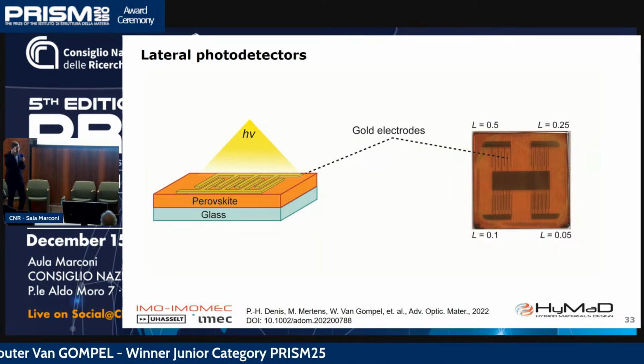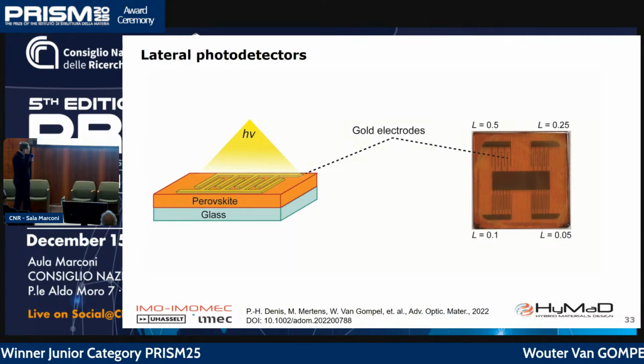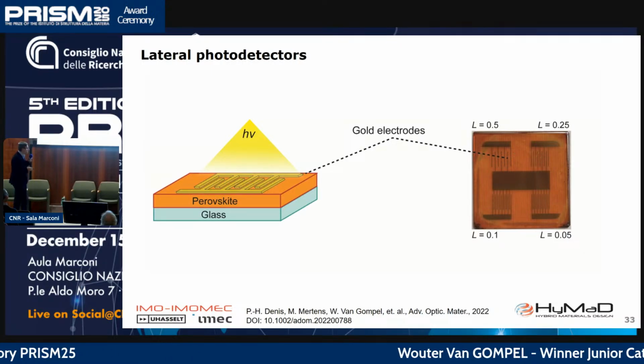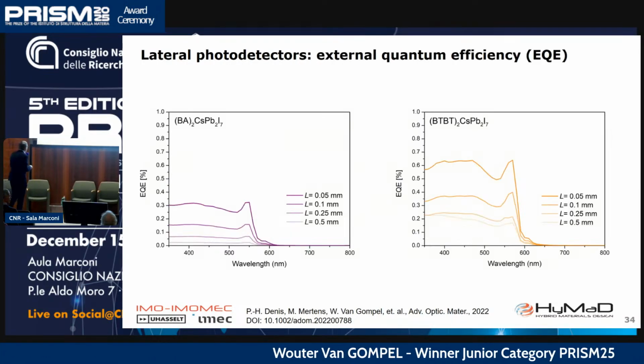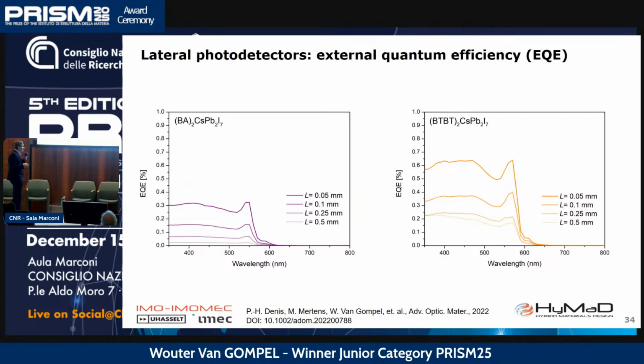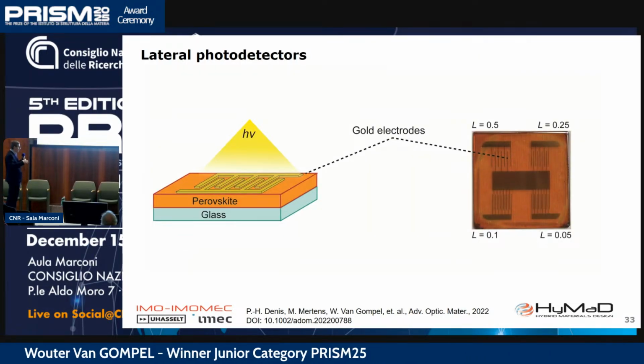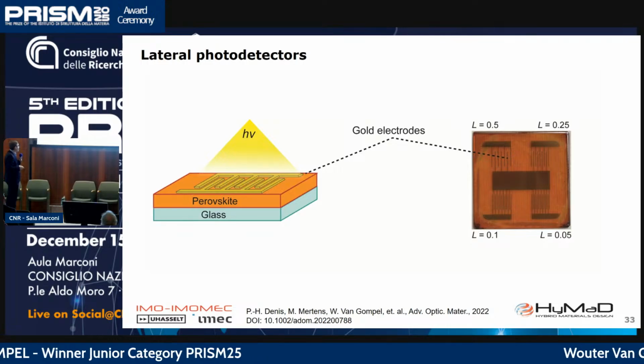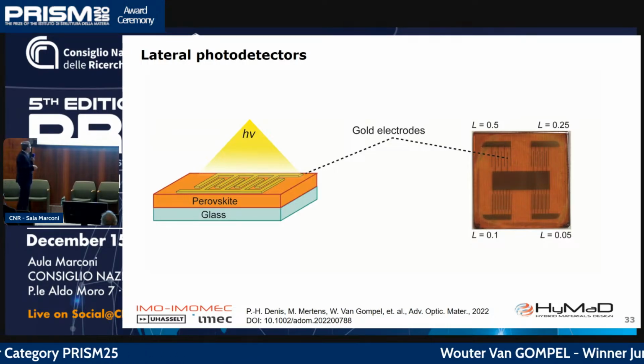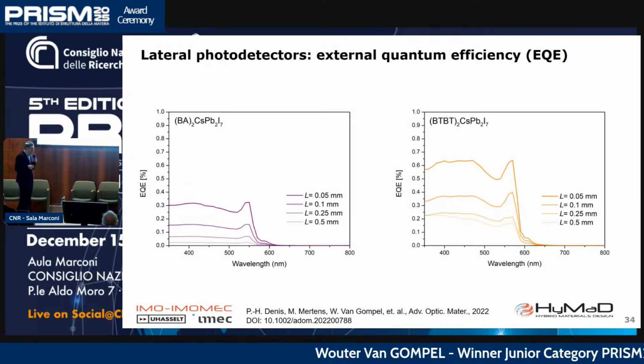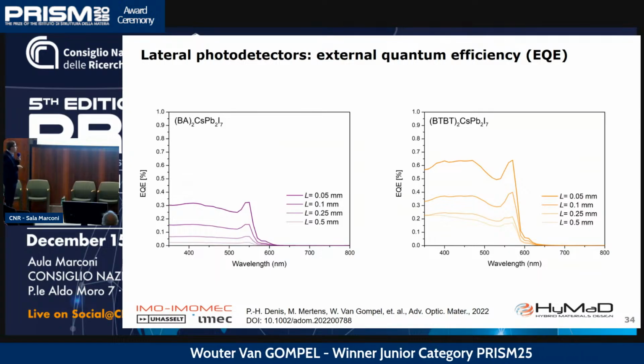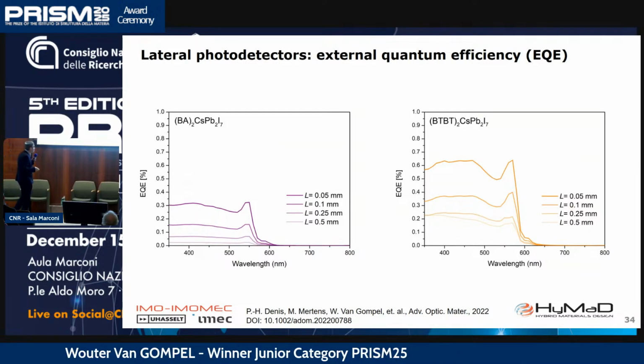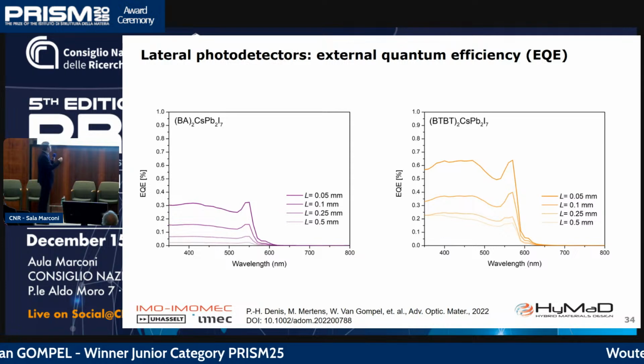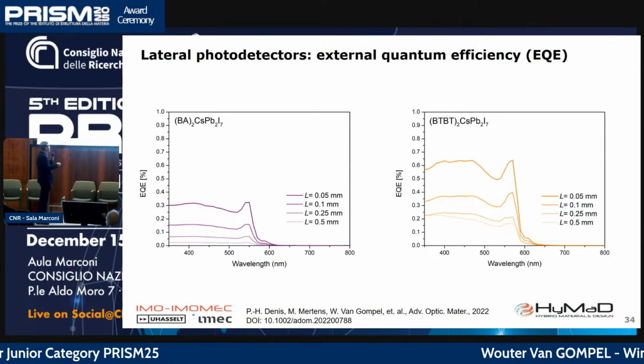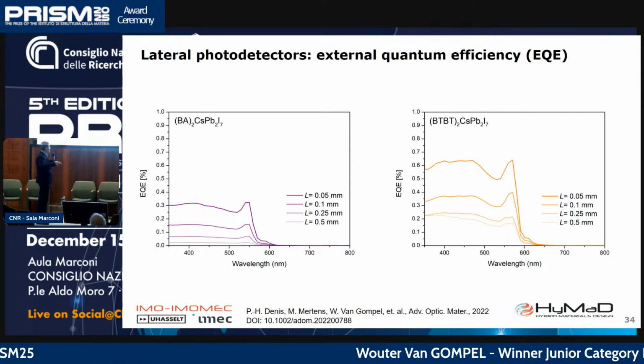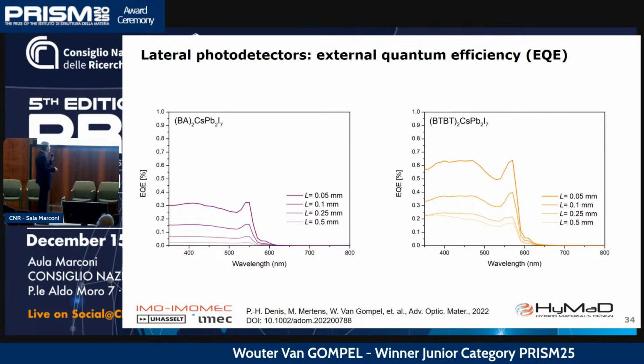And then, of course, we made a new material. It's still for optoelectronics, so hopefully the stronger stability doesn't destroy the optoelectronic properties, and it's not the case. So we made a very simple lateral photodetector, just evaporating some gold electrodes on top, applying a bias, and there you see that the external quantum efficiency of the new material outperforms the original one, so it performs better. Of course, with such a photodetector, the EQE is dependent on the bias voltage that you put on it. And so it's always a relative measurement.